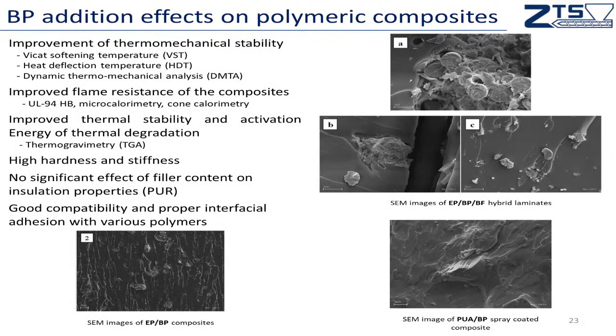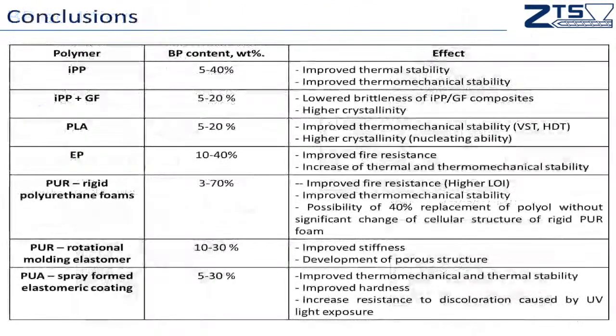Okay, so to conclude, if we move to the next slide, we can see that even if we use different materials, it can be polypropylene, it can be a hybrid composite containing glass fibers and the basalt powder incorporated in the polypropylene, PLA, epoxy resin, rigid polyurethane foams or elastomers manufactured by rotational molding, reactive rotational molding, or spray-formed elastomeric coatings, similar effects can be achieved. So the thermal stability and thermomechanical stability will always be achieved. The thermal conductivity and the flammability will be reduced.